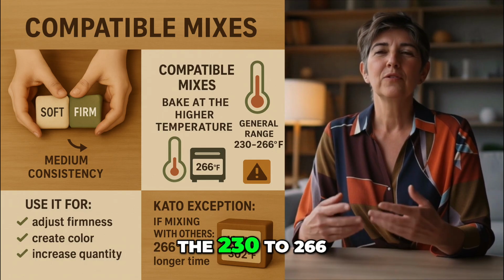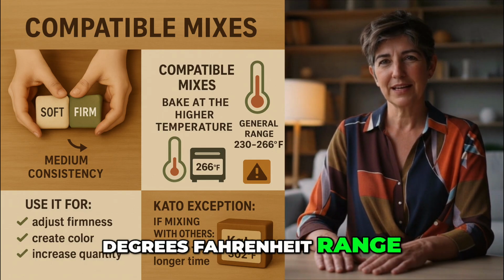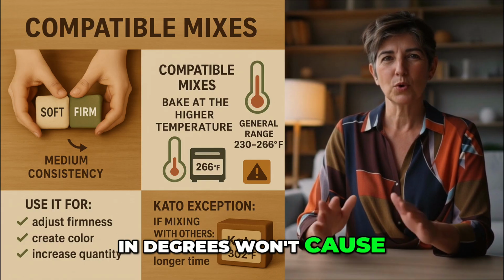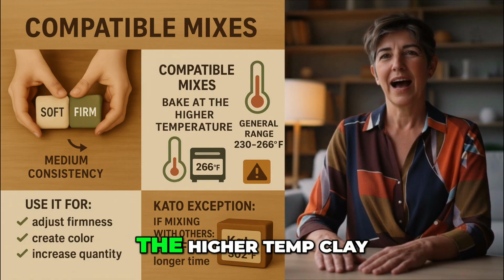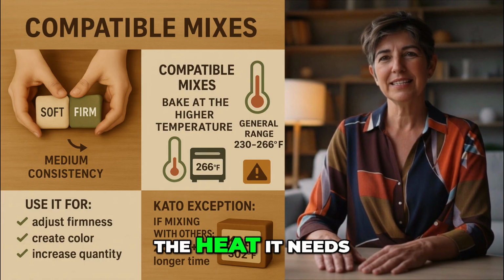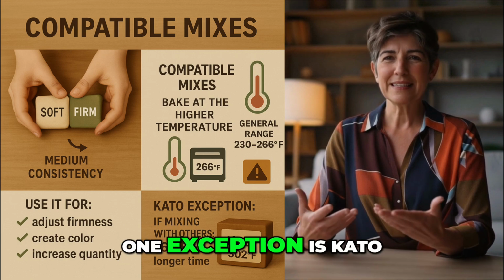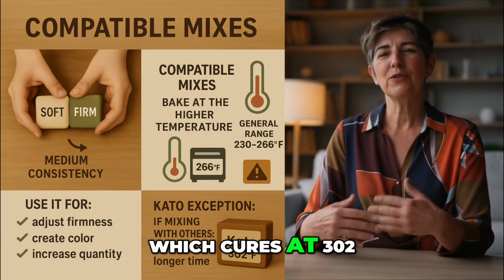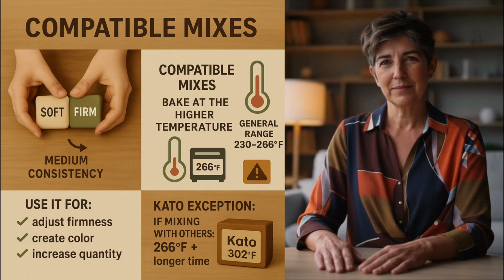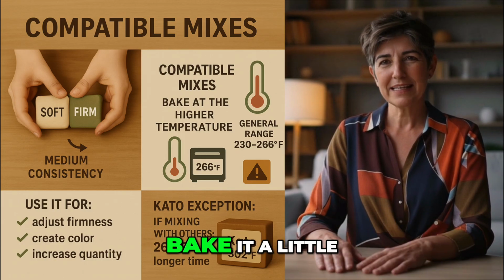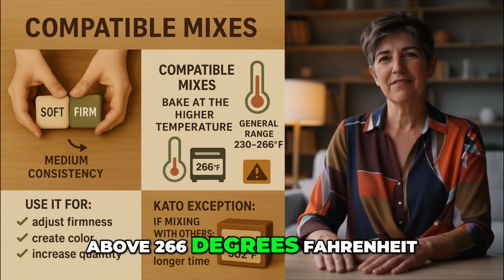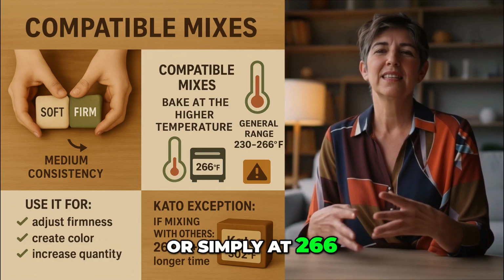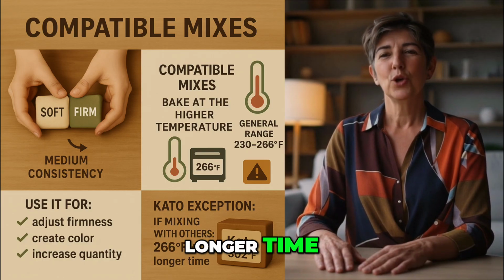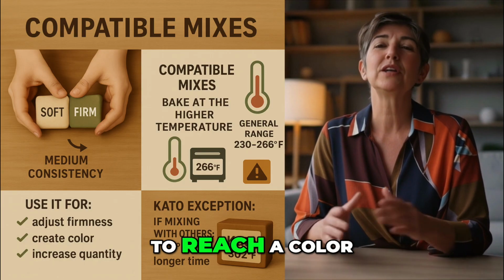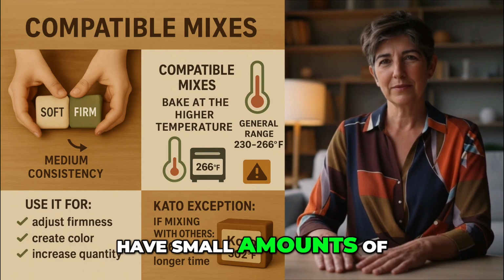Most clays bake in the 230 to 266 degrees Fahrenheit range. A difference that's small in degrees won't cause the lower temp clay to burn. However, the higher temp clay might not cure if you don't give it the heat it needs. One exception is Kato, which cures at 302 degrees Fahrenheit. If you mix it with another clay, bake it a little above 266 degrees Fahrenheit, or simply at 266 degrees Fahrenheit for a longer time. You can mix clays to change firmness, to reach a color, or simply because you have small amounts of two types and need more volume.